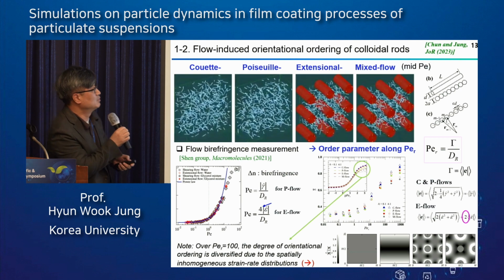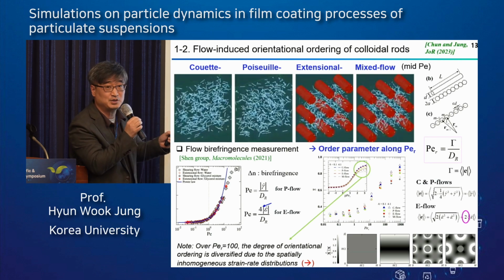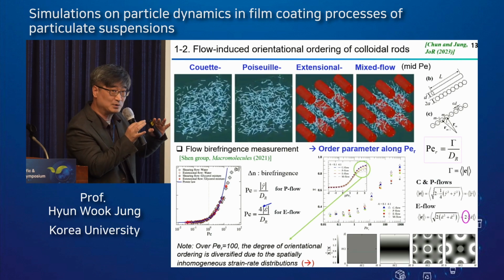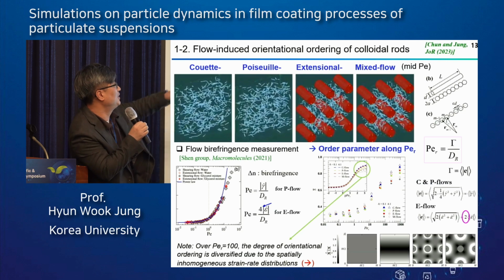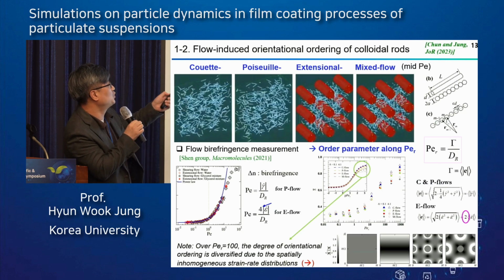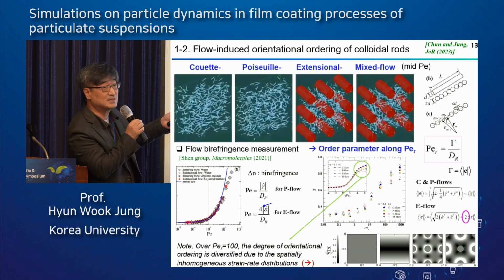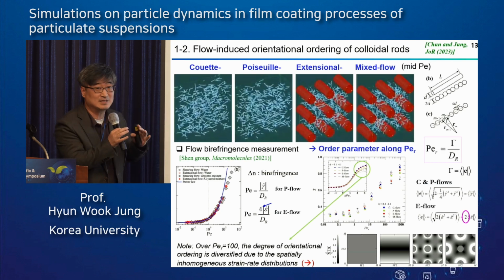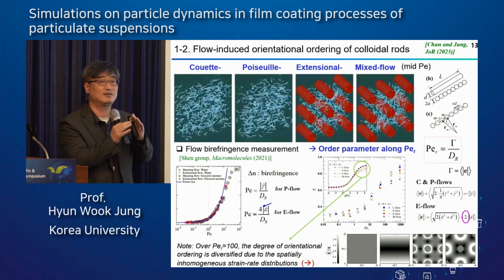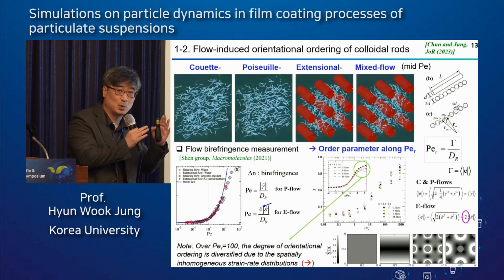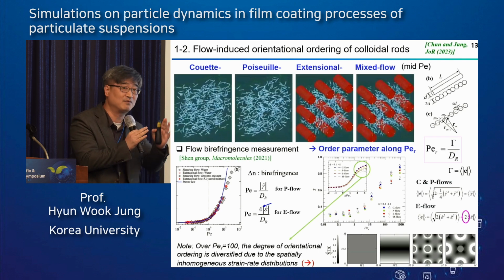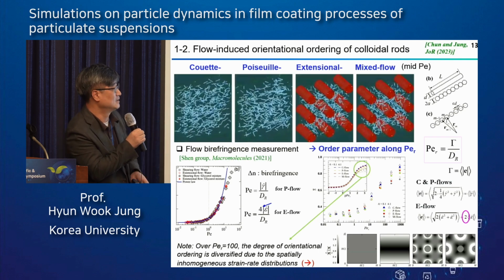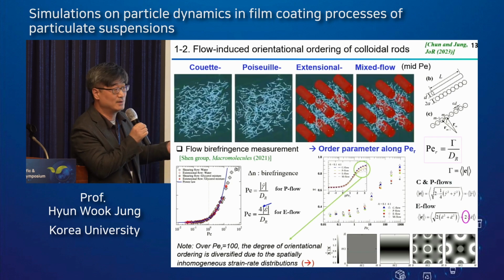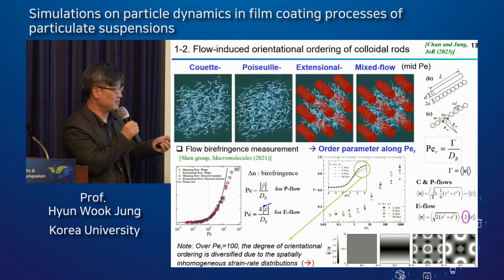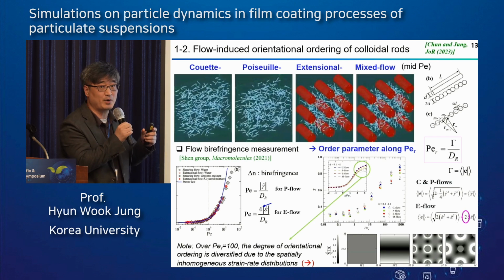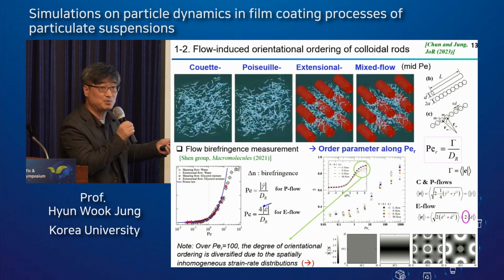Let's take a look at the movie showing the transient movement of semi-dilute to dilute colloidal rods in the various flow fields as shown here: quiescent flow, shear flows, extensional flow, and mixed flow cases. So based on this result, we can estimate the orientational order of colloidal rods following the flow field in each case, depending on the Peclet number, the rotational Peclet number. The rotational Peclet number is the ratio between the strain rate magnitude and the rotational diffusivity.